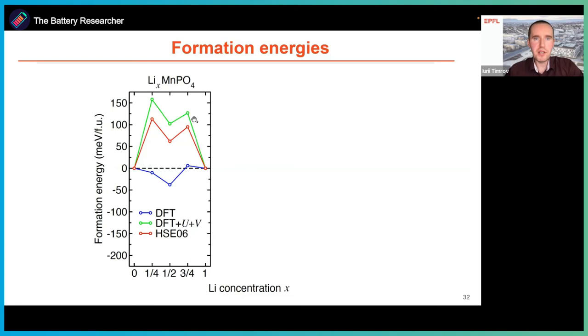So here, first, let's consider the manganese olivine. On the y-axis, we show formation energy in milli-eV per formula unit, and the x-axis is the concentration of lithium. And the formation energy is computed using three methods. So DFT fails, not surprisingly, while the other two methods, DFT+U+V and hybrid, are in agreement with experiments because formation energies are positive. And this agrees with the experimental observation of the two-phase process.